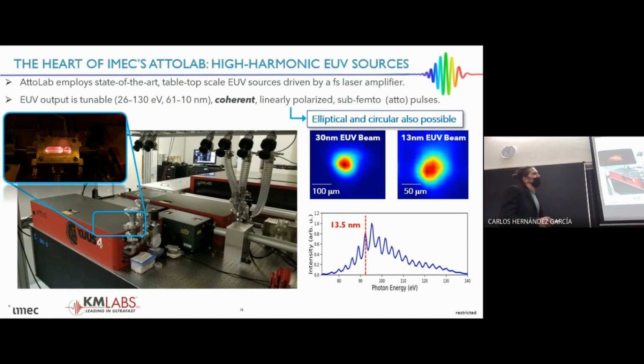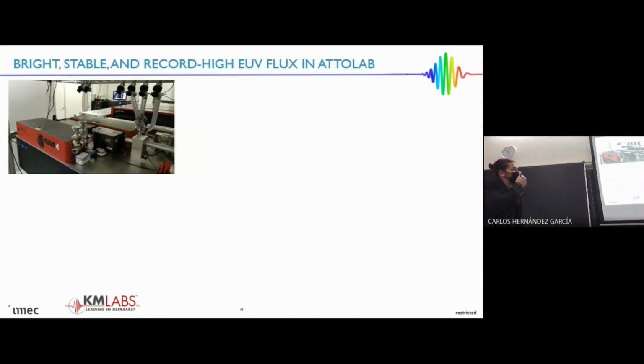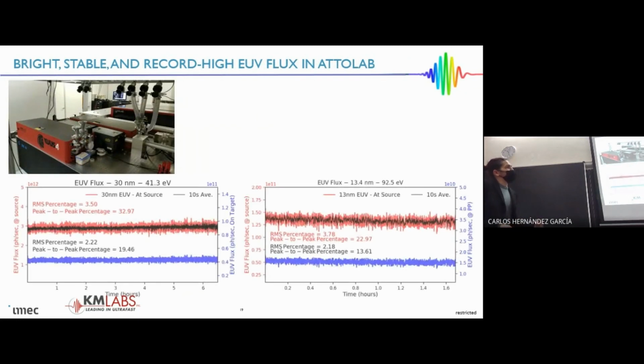And the way the system is set up, we produce a spectrum that almost peaks exactly at 13.5 nanometer, which is something a bit rare in HHG setups. It's often very difficult to get a spectrum that peaks right here. But with the engineering of this setup, this is a routine spectrum we get almost on a daily basis. And so with these systems, not only do we get nice spectra, we also have very nice stability out of them from this laser system.